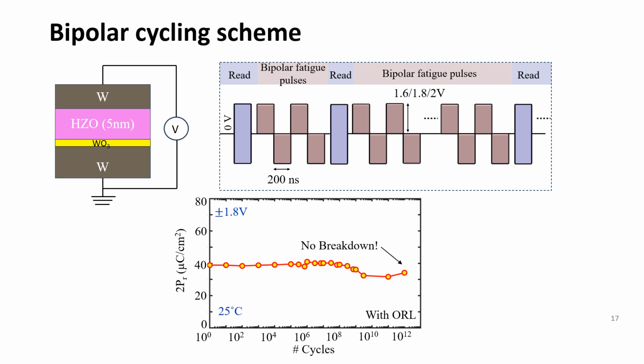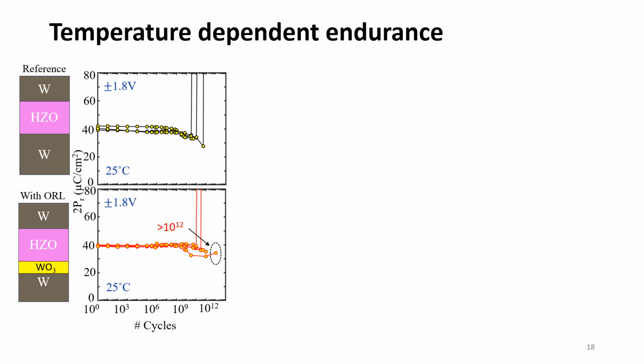So we could only see this data, but we wanted to show you a distribution across different devices of both the samples. Here you can see the top plot is coming from the reference device and the bottom plot is coming from the ORL device. In each case, we have measured 3 to 4 devices. And on average, we could see that the ORL device is surviving longer, or having higher endurance, compared to the reference device. These measurements were done at 25 degrees Celsius for 1.8 volt of fatigue pulses.